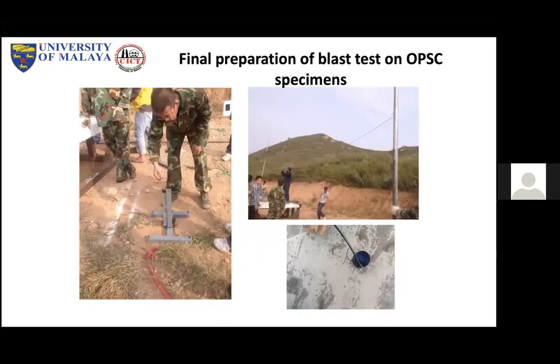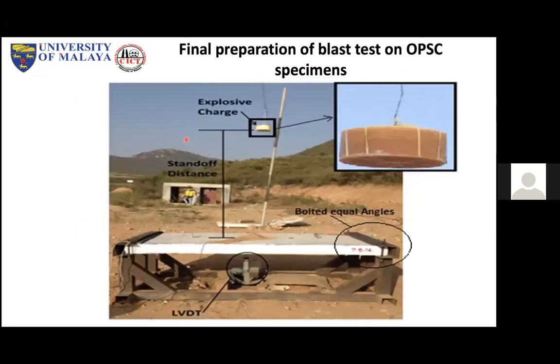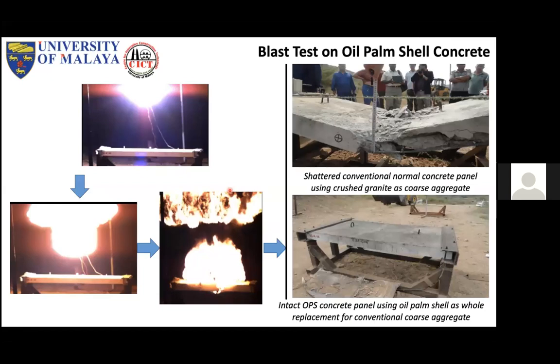This Professor Zha is the expert in explosives. He can handle them because he is trained and licensed. So he helped us with the actual explosive, 10 kg TNT. We had a standoff distance of 1.5 meter height. It's quite close. This is the explosive charge, and the 1.5 meter standoff distance. And we did the test. You see the comparison: the normal weight beam or slab almost shattered, nothing left after the test. But the lightweight concrete can withstand the blast after the 10 kg TNT.